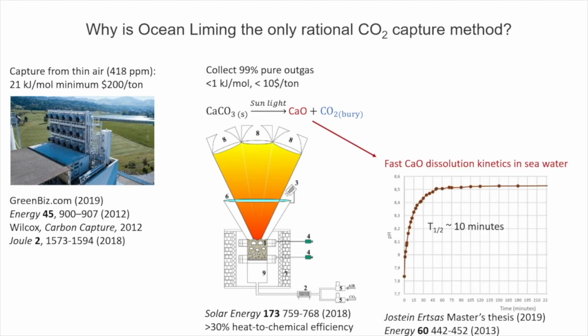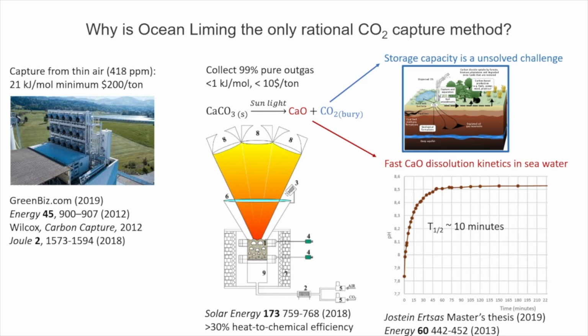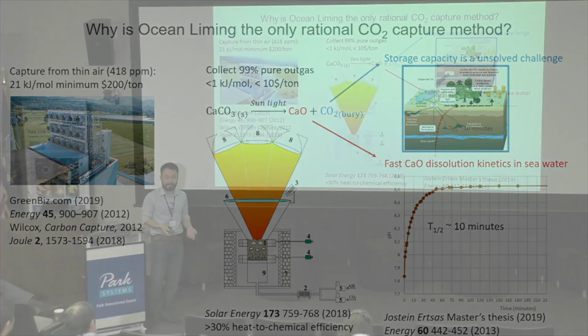And this quicklime, a talented master's student, I think in Norway, just studied the kinetics of quicklime dissolution in seawater, and it dissolves very, very well, on the order of tens of minutes. So if you sprinkle it, before it reaches the bottom, it will have completely dissolved. So that's very encouraging. But both methods of CO2 capture have one common bottleneck that needs more research. What are we going to do with the CO2 that we either capture or we produce on site?